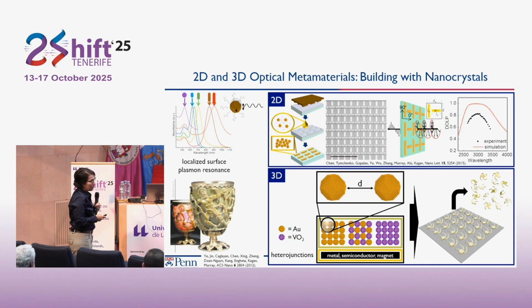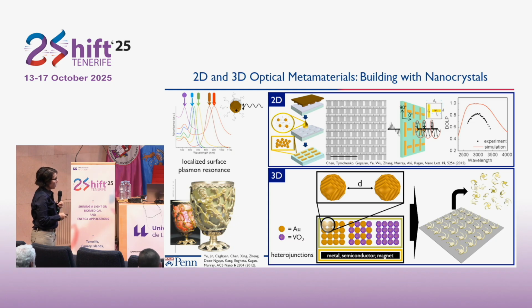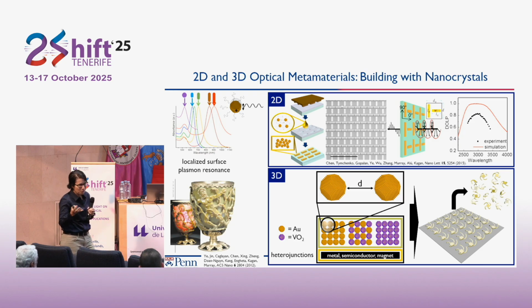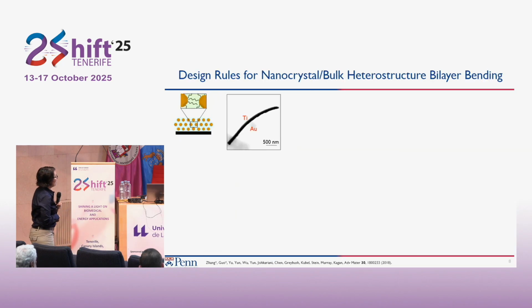What I won't have a chance to tell you is that you can also release these structures from the surface and suspend them in solvent. We've played games with how you can manipulate them with acoustics or magnetic fields, and we're playing right now with optical trapping as well. But the key to this is to think about what's different about nanocrystals from the evaporated film if we put a nanocrystal layer on a thin evaporated film. That allows us to really address the nanocrystals, and the bulk film underneath doesn't care. I'm going to tell you through this in just a moment.